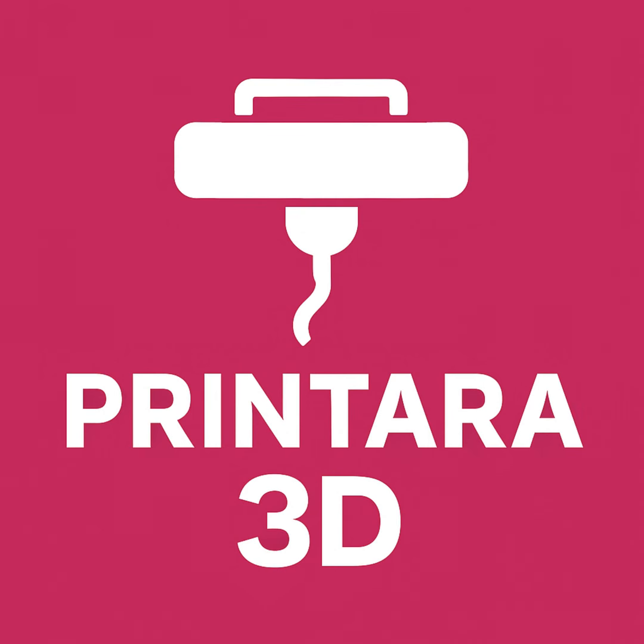Now, it does have one little printing quirk that annoys some people. It tends to form these thin, kind of hairy wisps between different parts of the print as the nozzle travels. We call it stringing. Ugh, stringing. Yeah, I've seen pictures of that. Looks messy. It can be, but don't let it scare you off. You can usually tune your printer settings, especially retraction, to really minimize it.